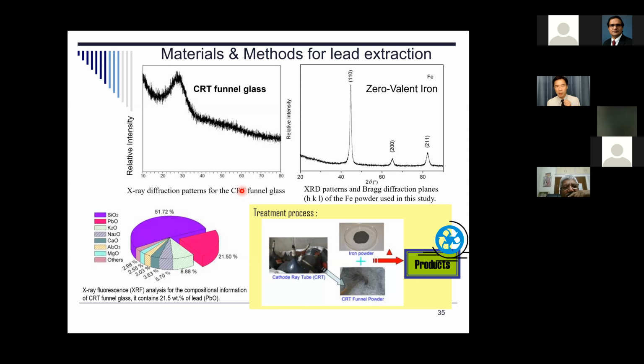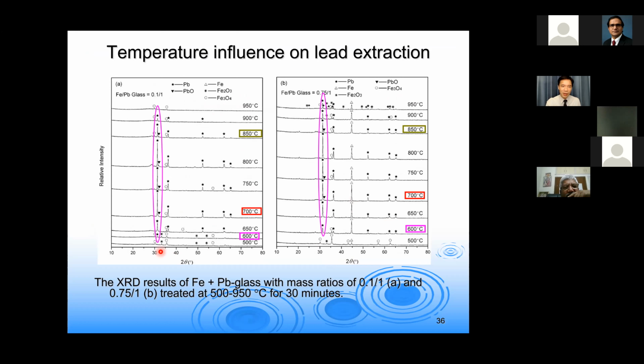And we thought about one possible way, which is to use zero valent iron, because zero valent iron powder, or basically iron cuttings, that kind of residue, can be used. So we mixed this zero valent iron powder together with the CRT funnel glass, and we found something very interesting. Yes, we did it. We reduced the lead ions in the glass matrix into metallic lead. The evidence is here, we start to see metallic lead coming out. It shows up around 600 degrees Celsius, as a very weak signal, but miraculously it disappears at relatively high temperature.